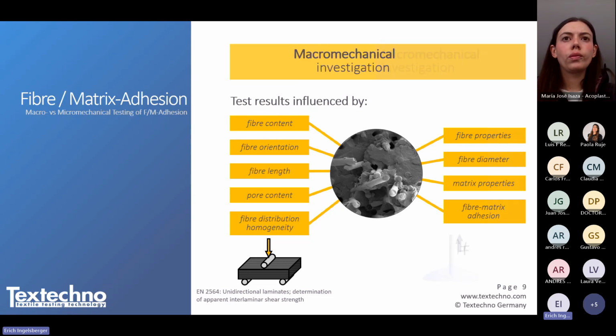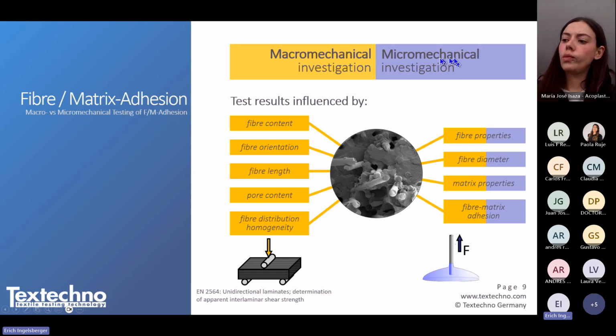We instead choose to use micromechanical testing, which is the test of only one single fiber. Thereby we can exclude all these falsifying parameters, these falsifying effects, and only concentrate on fiber properties, fiber diameter.